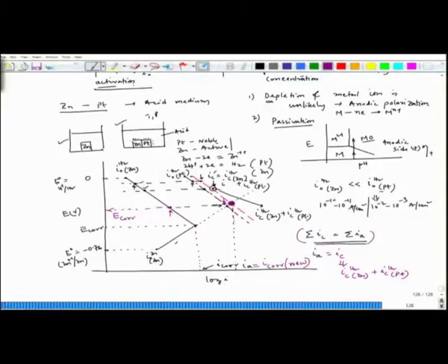Now, when there was no connection between zinc and platinum, only in this case, I had this current density for the corrosion; this particular current density was the corrosion current density. But as we have connected to platinum, which is a noble component, I could see that the current density for the corrosion has gone up enormously, because you remember this is a log scale.